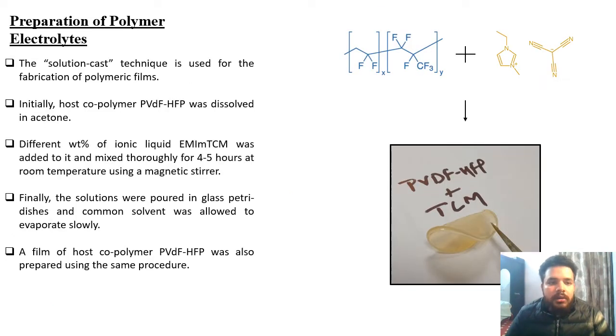So this is the method which I have used to prepare polymer electrolyte. I have used the simple solution cast technique. First of all, I have taken PVDF-HFP as a host copolymer. Then I have dissolved it in acetone, and when it is completely dissolved, I have added different amounts of ionic liquid. The ionic liquid I have used is EMIM-TCM, 1-ethyl 3-methyl imidazolium tricyanomethanide.